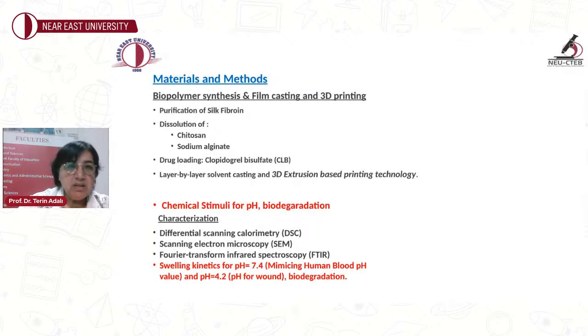So what we have done: we purified silk fibroin from Bombyx mori silk cocoons, and chitosan and sodium alginate were also dissolved and used. Of course, in order to improve the hemocompatibility property, clopidogrel bisulfate is embedded within the structure, and we use 3D extrusion-based printing technology for the three layer-by-layer structure of these polyelectrolyte complexes. So chemical stimuli have been tested for pH and biodegradation.